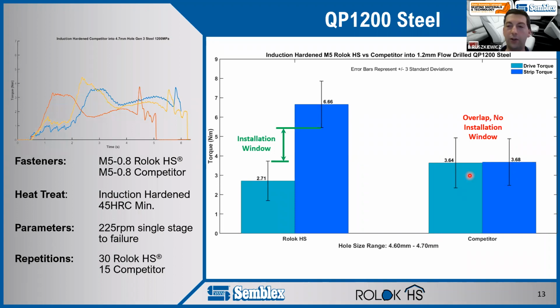If you remember that simulation early on, even though those threads collapsed on the traditional thread rolling screw, it still did form a little bit into that steel. But on this 1200 steel, it didn't form in at all. We flattened out all the thread crests, bent them and collapsed them, never formed any threads into the steel, which is why our drive and our strip torques are exactly the same. If we look at this curve on the left, early on we showed a drive to failure curve where you had that nice low peak and that nice high peak. You don't get that with a traditional thread rolling fastener in this steel. Our drive torque and our strip torques are about the same.